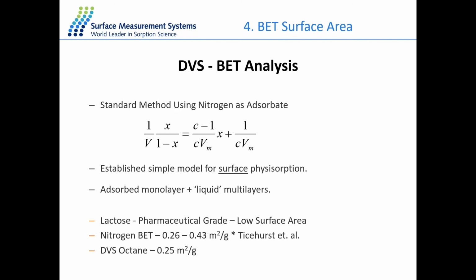And it is quite important that you get a type 2 or type 4 isotherm with a monolayer region for the calculation of the BET surface area. And what we normally use is some organic vapors like octane or ethanol as a probe molecule, and you just do the sorption of the probe molecule organic vapors. Then from the points inside the BET range, which is between 0.05 and 0.35, we can get the BET surface area of the material.